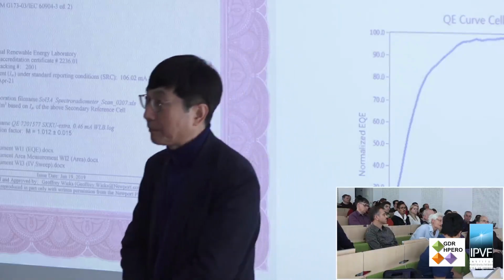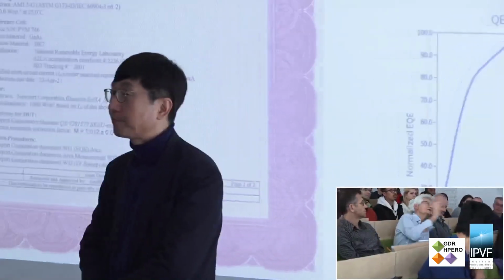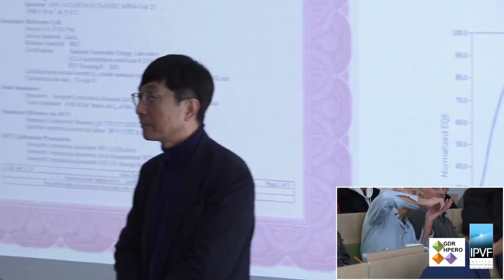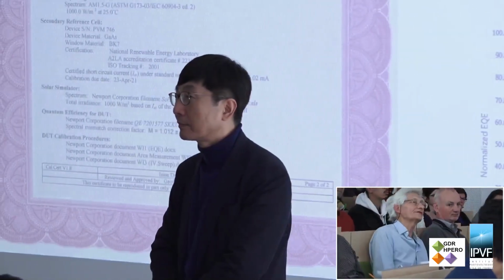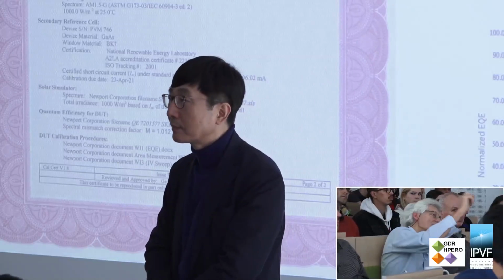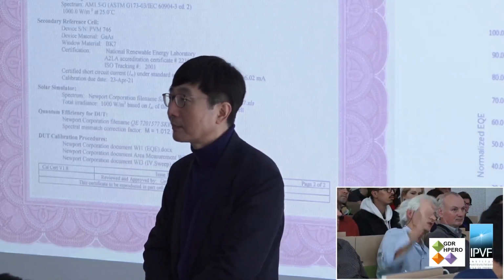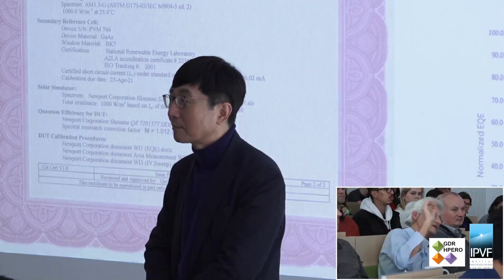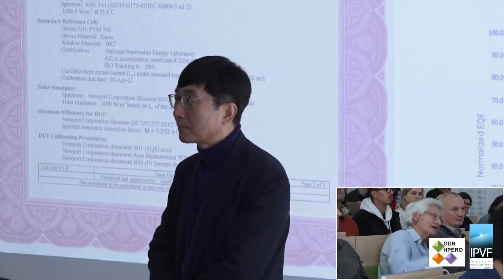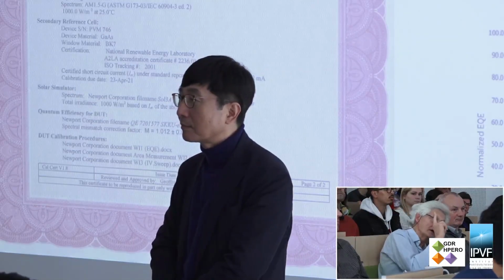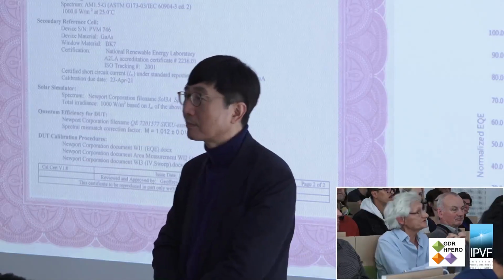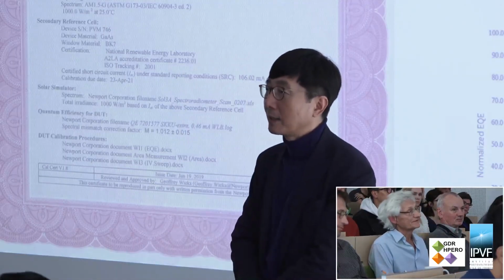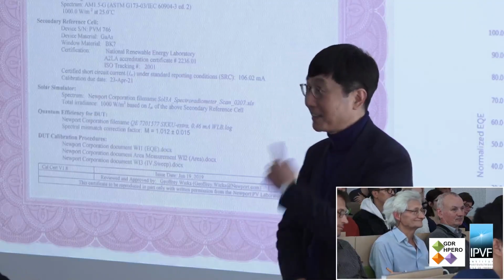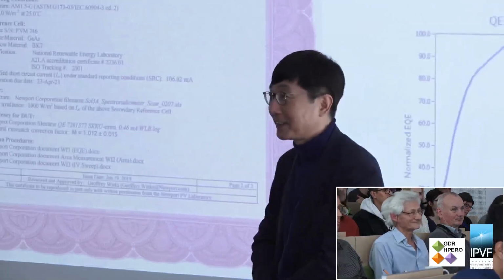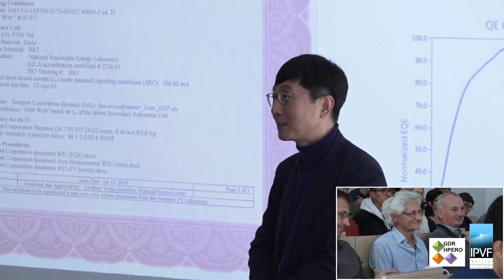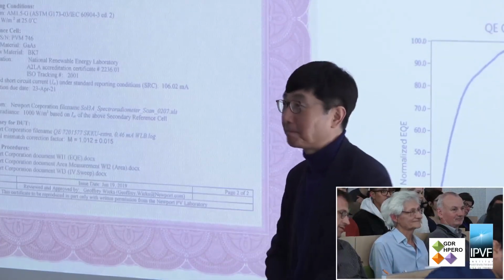There are a lot of DFT calculations. But these DFT calculations give a very spread value for the energy of formation, between 0.2 and 0.6 electron volt. Between 0.2 and 0.6 electron volt, this is a ratio of 3. This is very important for the activation energy for the formation of these point defects. I see. Okay, so I will study further to figure out this kind of defect. Thank you.